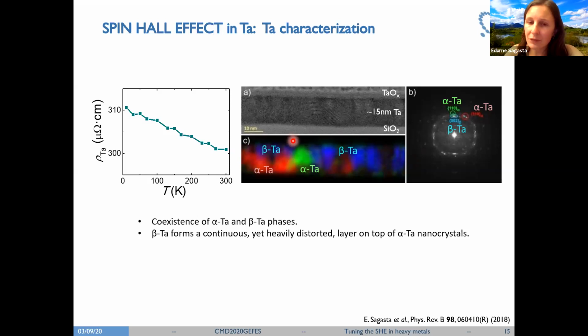And this is important for us because in the lateral spin valve, we will have the spins arriving from the copper channel that will be injected at the top side of the tantalum nanowire. So the spin to charge current conversion will occur in the top side, so in beta tantalum. And importantly here, what we can say is that just measuring the resistivity is not enough to determine the phase.